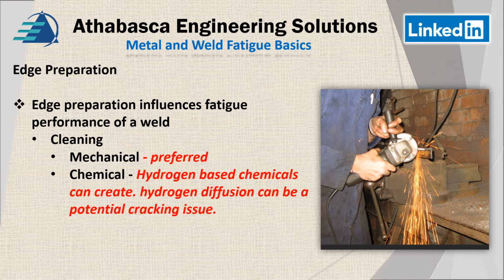method. There's another method, which is chemical cleaning, and the problem with it is that these chemicals have hydrogen, and these hydrogen-based compounds can create hydrogen diffusion, and it can potentially create a cracking issue, because you've got to remember the part is getting really hot when you weld it later after cleaning, and the surface can have some hydrogen which can go inside the steel. That would be more of a case with a carbon steel or an alloy steel, where that's a big situation. But again, I think the industry standard, at least in Canada, is mechanical.